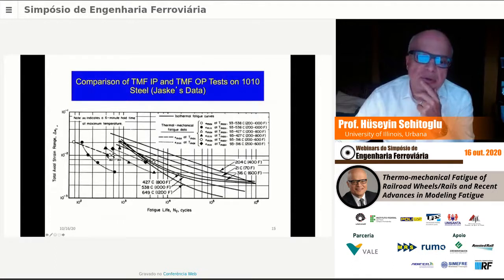Some of the early data on thermomechanical fatigue is shown here. So this is strain range, this is fatigue life, right? So the isothermal results are shown here with solid lines. This is 1010 steel. This is not a railroad steel. It's like a boiler tube steel, low carbon steel. So all the isothermal data is here, right? It has the metric units: 204, 21, 316, 427, 538, 649 degrees. So this is the high temperature. Of course, the fatigue life for the same strain range decreases as you go to higher temperatures.